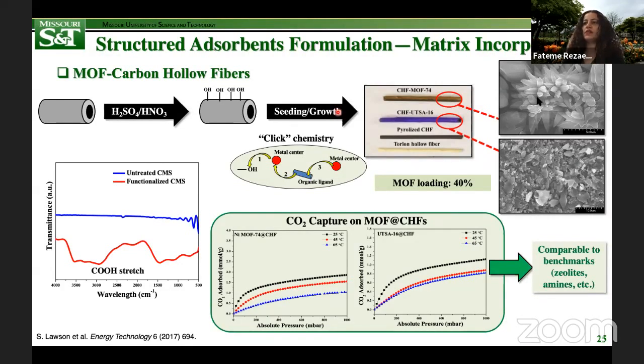Specifically looking at MOF-74 topologies, we notice a flower-like structure here. And as opposed to what has been reported in the literature, we believe that this might have been caused by the OH groups deprotonating the ligand and forming a structure which is not interconnected. This approach gave rise to relatively low MOF loading, around 40%.